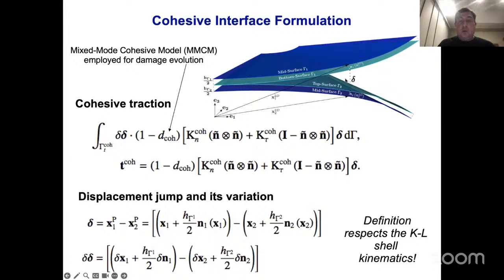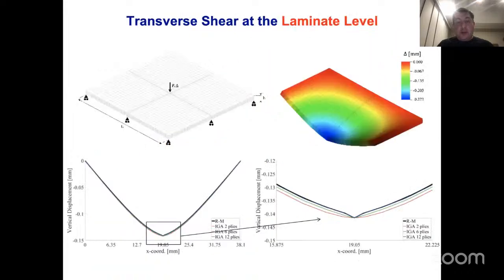And so we look at the two adjacent plies. We go to the mid-surface positions in the current configuration. Then we extend those to the boundary, using the normal vector on each ply and half of the thickness. And then the difference between these two quantities gives me the displacement jump. Again, the key idea here is that your displacement jump respects the kinematics of the Kirchhoff shell.